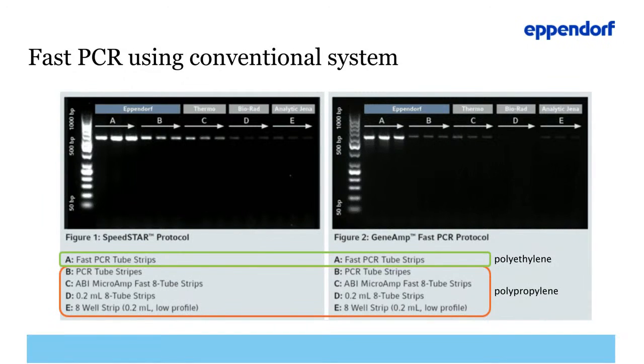Studies conducted to compare the amplification results of this polyethylene tube with different polypropylene vessels under the same condition showed vastly improved amplicon yield. This means that using this kind of vessels, you can potentially cut down on PCR holding times or number of PCR cycles, hence achieving shorter time to result. Moreover, this polyethylene fast PCR vessel is suitable to be used to troubleshoot low-yield amplification. There is no need for additional investment into special devices or systems, so the cost of stepping up productivity is much smaller.